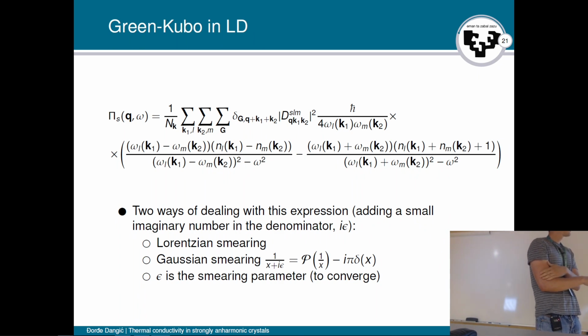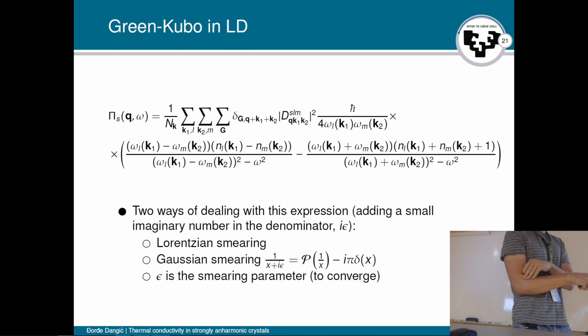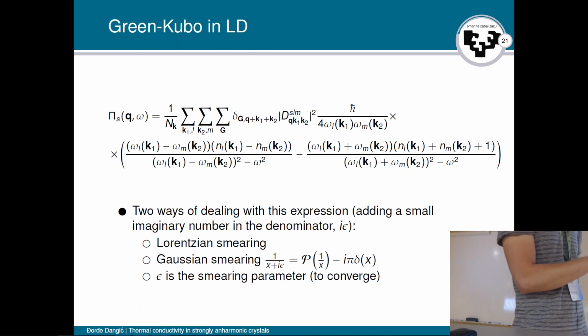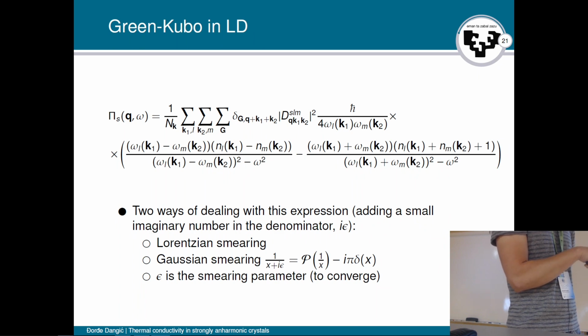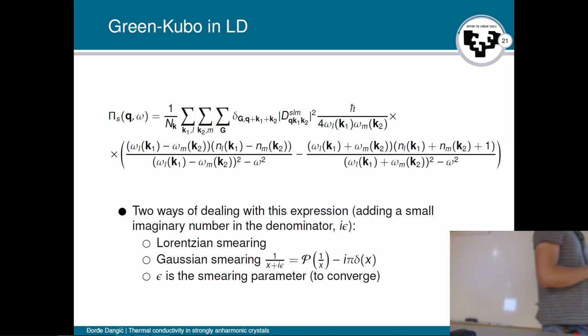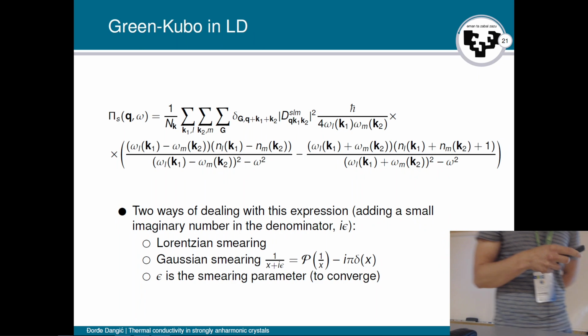However, we can use this identity to actually split this phonon self-energy into the real and imaginary part, where the real part is the principal value of this integral, and the imaginary part has this delta function. And now that we have the delta function, we have to somehow approximate it in the numerical procedure, and we are going to use the Gaussian function, and then this approach is called the Gaussian smearing. So there are two different ways of dealing with the poles in this thing, but in both cases you have something called the smearing parameter, which is a convergence parameter during the calculation.